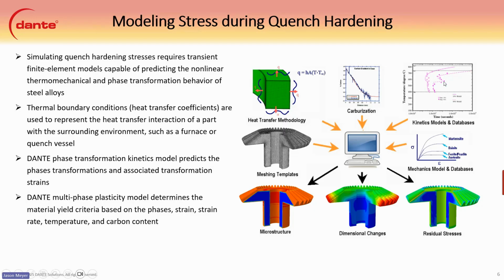We have phase transformation kinetic models that predict the phase transformations and associated transformation strains, and this is really kind of a big part with steels here, like we talked about earlier. And then our multi-phase plasticity model determines the yield criterion of the phases. The strain rate, the temperature, and carbon content all go into that multi-phase plasticity model to really get the mechanical properties down. And what we get out of it is microstructure.